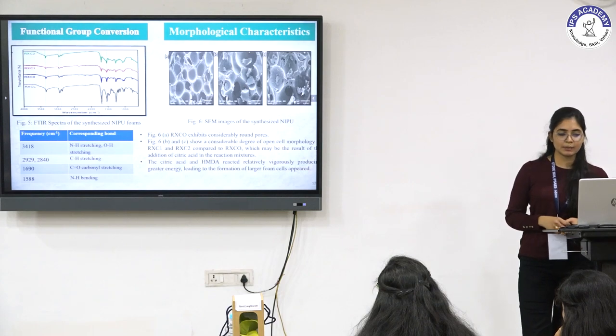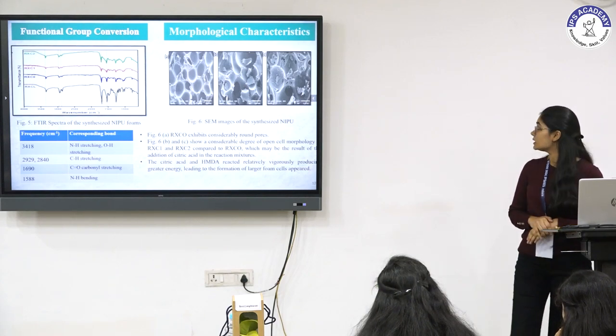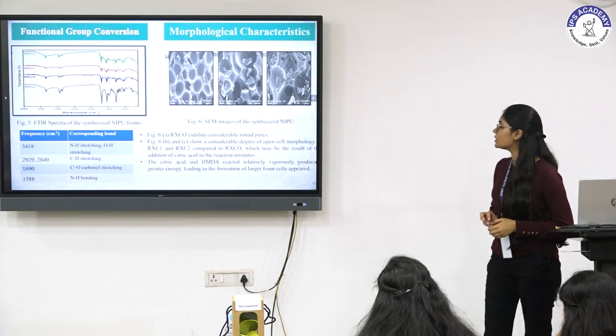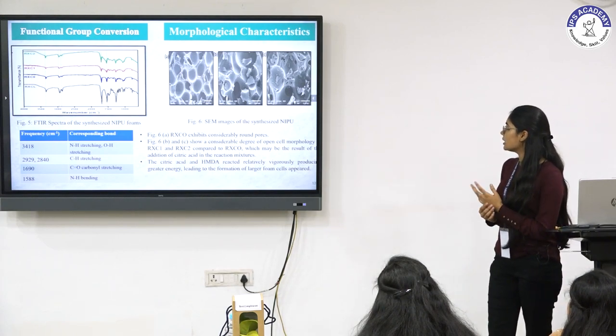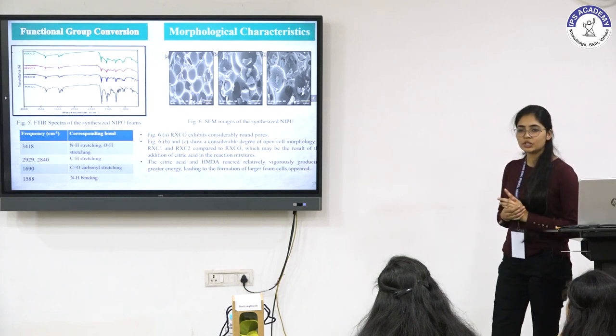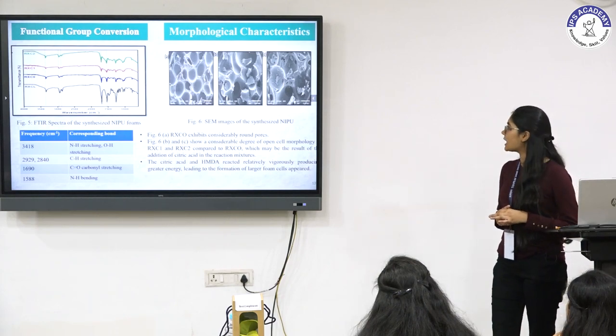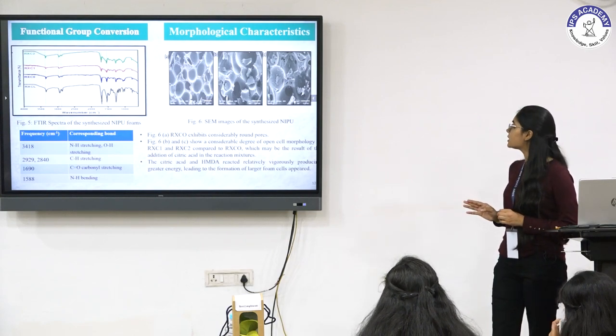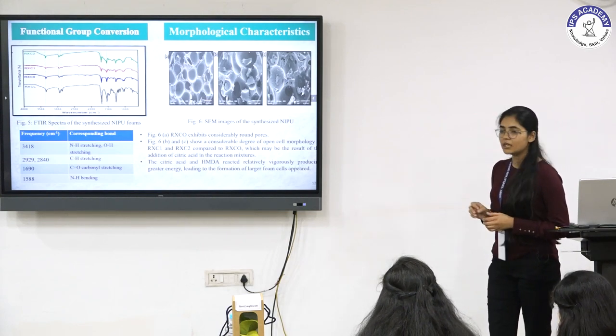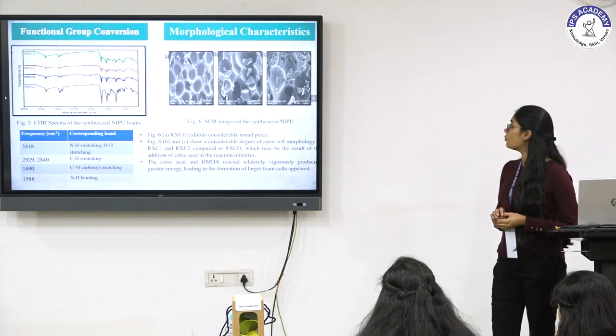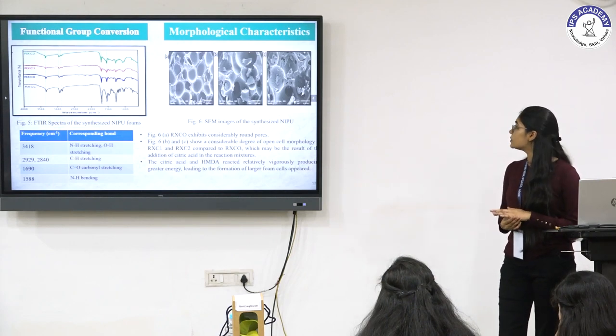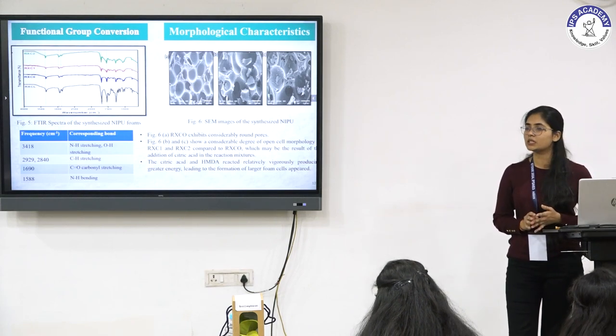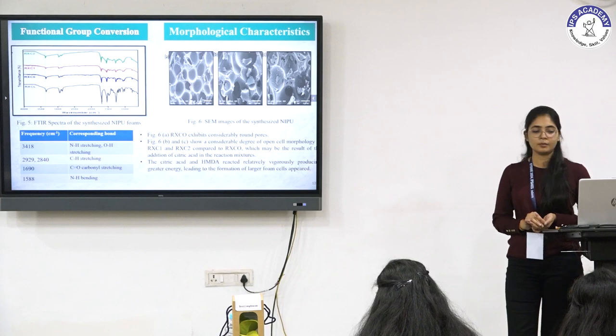Next is the SEM characterization of these NIPU foams. Figure 6A represents the SEM image of RXC0, which contains 0% citric acid. On moving from A to C, the amount of citric acid increases. With increase in citric acid amount, open cell morphology is observed and the cell size also increases. This is due to the vigorous reaction between citric acid and hexamethylene diamine.